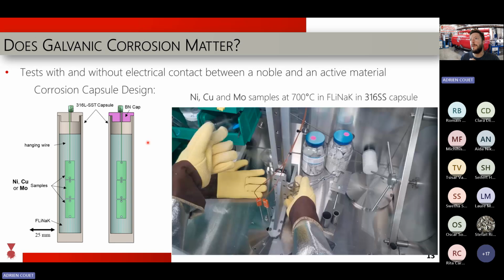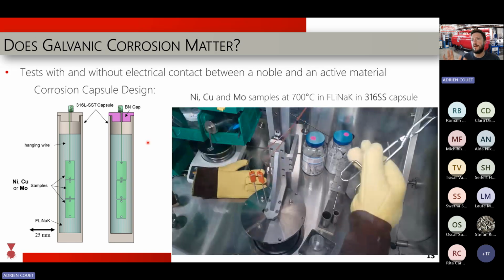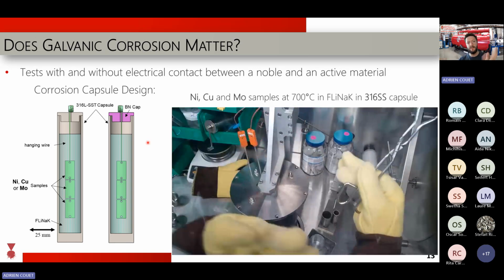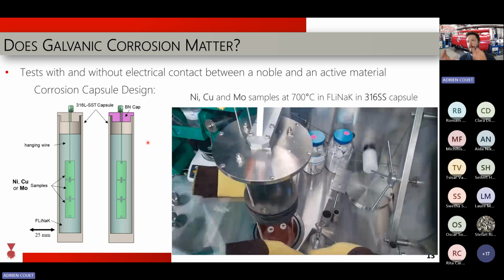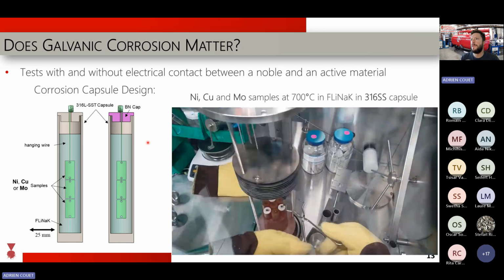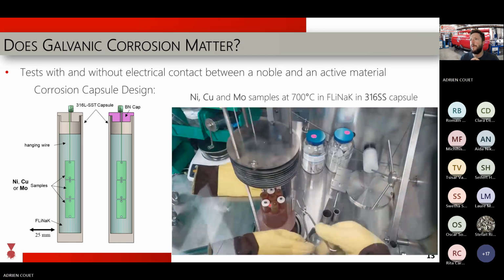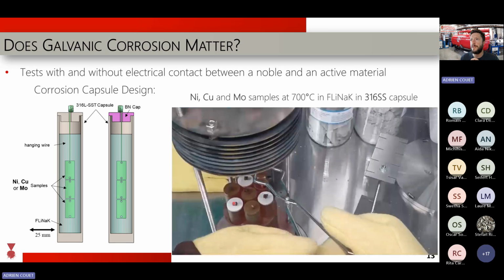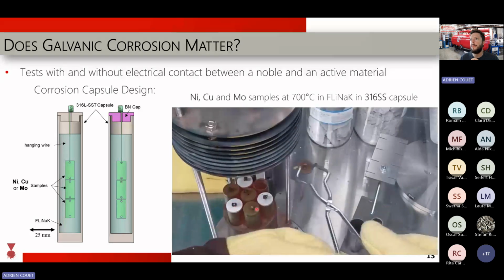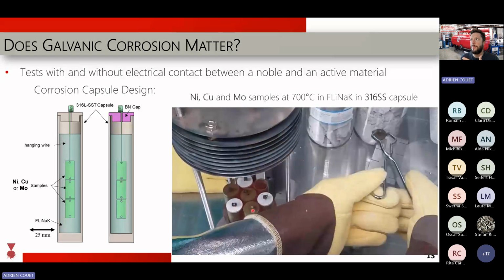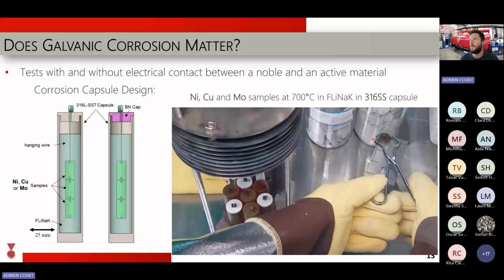So this is the kind of test we do. This is in a glove box. We have a well, we have a furnace around the well, and then we take those capsules out of the glove box. So here you can see the nitride caps that are preventing electrical contact, and then we have those stainless steel caps that remain electrically connected, right? So we take those samples out.